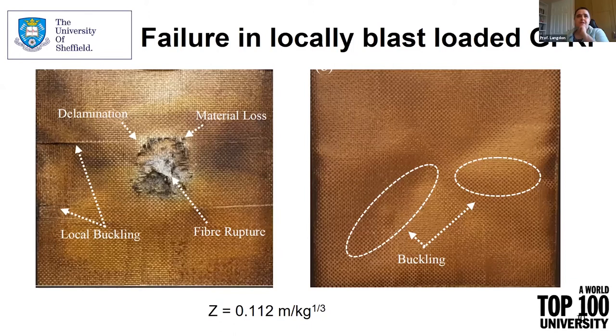But you can see that the observed failure modes are very similar. You've got delamination of the layers, you've got fiber rupture, loss of material when the loading is very intense in the center of the panel, rather than backed off further away, fiber rupture. And because of the higher thickness of these particular panels, we also see some other effects. On the right-hand side, when you're looking now at the back surface, you can see that there's some buckling. The panel surface appears to be wavy. And the material that's been lost in the center on the left-hand side is due to the fireball interaction with the material. Because the scale distance is extremely close, this is a very, very near field explosion, meaning that the fireball itself will interact with the material, and in this case, potentially burn some of it away.